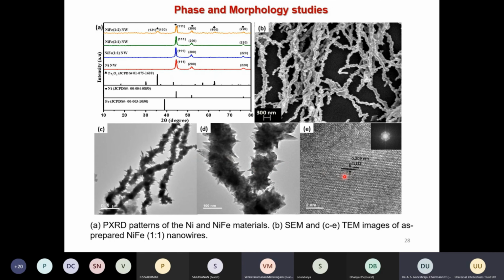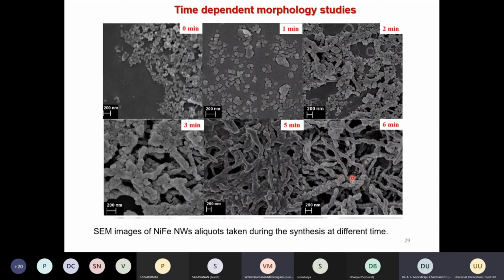But what we see is a very crystalline material on this one. Maybe the XPS indicates that there is a small amount of nickel oxide present on the surface. Okay, so then we try to understand why the nanowire formation happens.